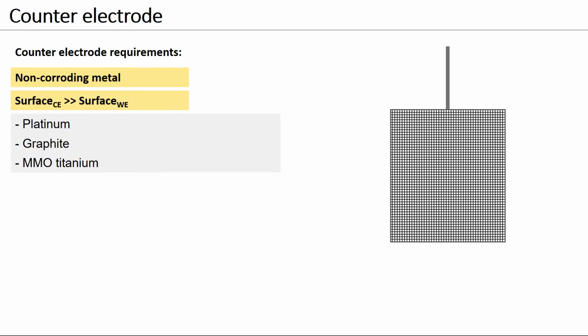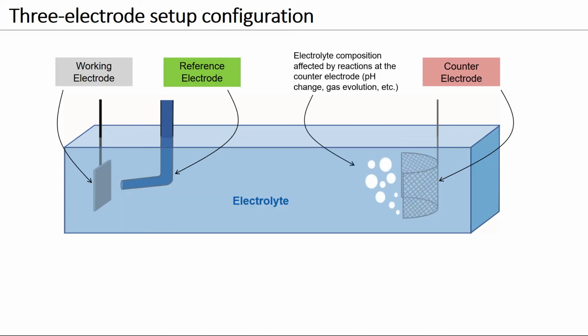It's recommended to ensure that the surface of the counter-electrode is larger than the working electrode, to avoid that a possible kinetic hindrance of the reaction at the counter-electrode limits the system. To achieve a large surface area, counter-electrodes are sometimes in the form of a mesh. To avoid that the electrochemical reactions occurring at the counter-electrode immediately change the electrolyte in vicinity of the working electrode, the counter-electrode is ideally placed at a relatively large distance from the working electrode. Note that the reference electrode should be placed in close vicinity to the working electrode. This allows minimizing possible measurement errors, such as effects related to the ohmic drop.